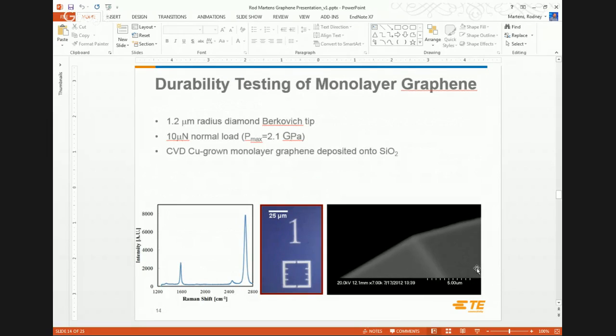Well, durability testing of monolayer graphene, this work was done by Professor Terrell's group at Columbia, where they took a blunt Berkovich tip. So this would be in a nanoindenter, where typically this radius would be in the order of nanometers, but for this exercise, it was blunted so that we can use it as a tribology tool. We're operating in loads of 10 micronewtons, and then the CVD graphene was grown on copper, but then it was transferred onto silicon oxide in the little square area shown in the center there.